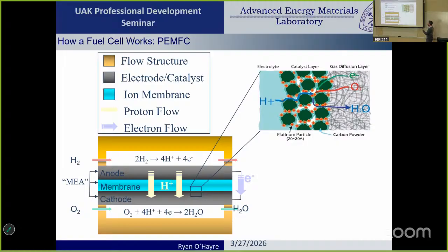And so when we try and design this interface for fuel cells, it's almost as much of a black art as it is a science. What we're trying to do is maximize the number of these triple phase boundaries. If you do this well, you can get an effective surface area for catalysis that's as much as 1,000, 2,000, 3,000 times larger than the geometric area, the projected area, right? So if you had a 1 square centimeter fuel cell like this, it could actually have like 1,000 square centimeters effective catalyst surface area there at that interface.